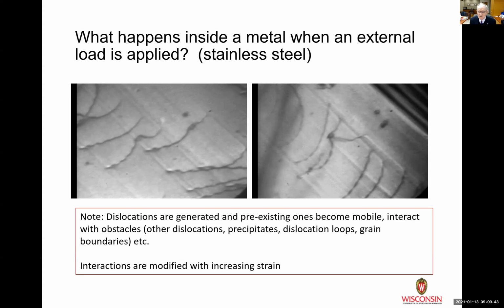And what I want you to do is focus on the dislocations that are around the precipitate, and watch how the dislocations break away and move past that precipitate, right? The precipitate's an obstacle, and we're going to see how the dislocation goes past. This is what's happening inside a material when you apply a load to a bulk specimen. So let me see if the first one will play.